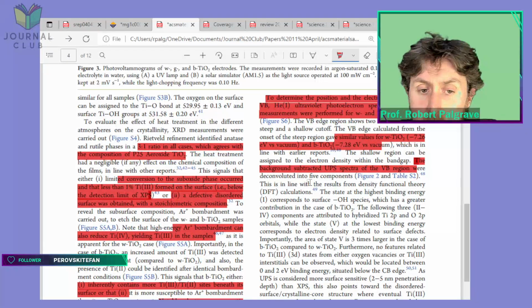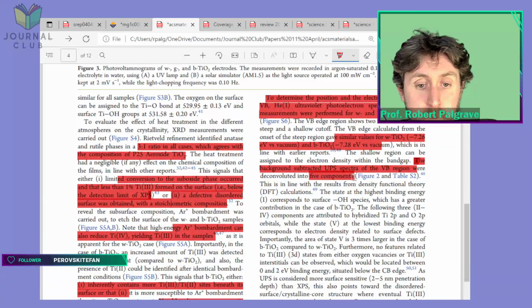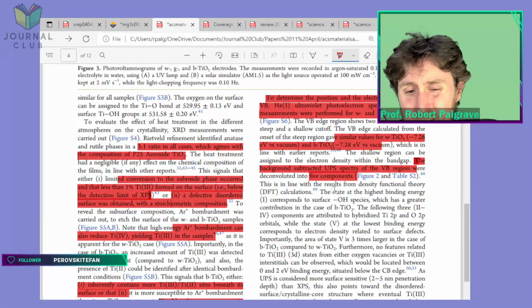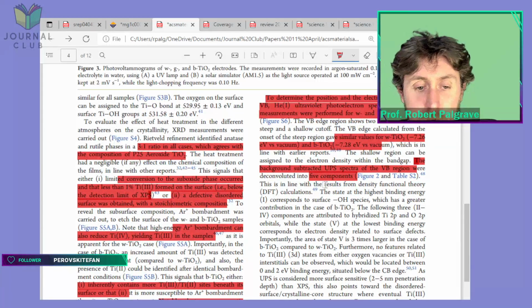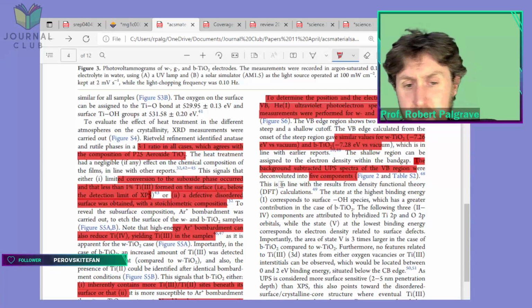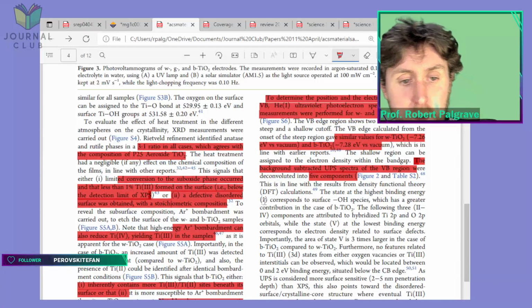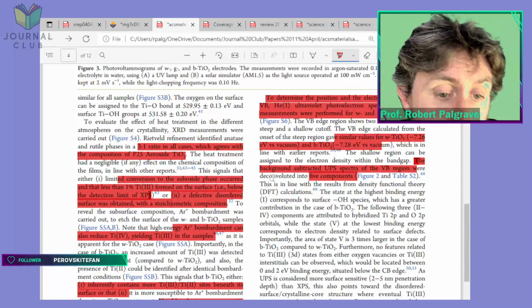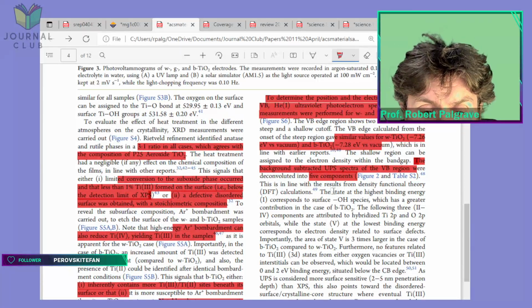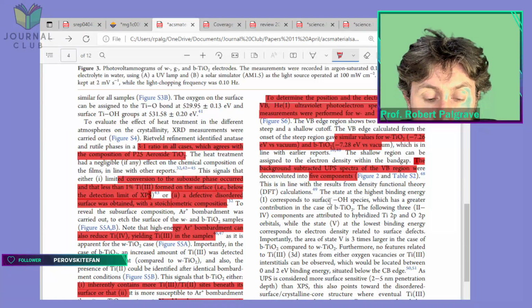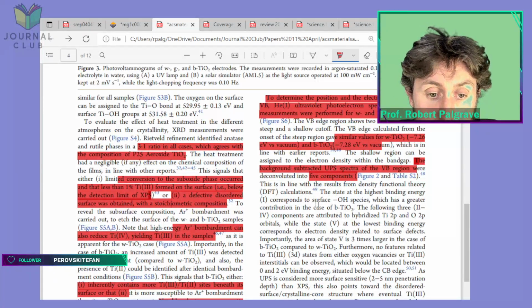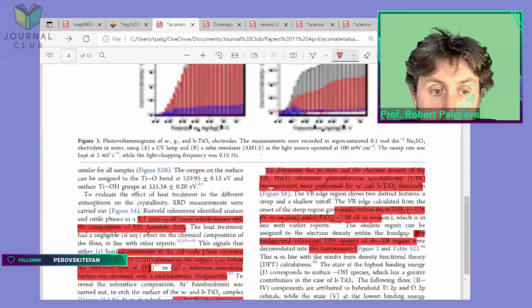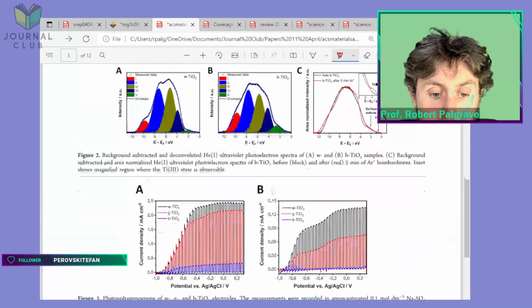I'm pretty sure the DFT paper is not going to say there are 5 components in this valence band, because that's not language DFT people speak. They like to talk about partial densities of states. I don't think they're going to say there's 5 things. But anyway, maybe they will. The state of highest binding energy corresponds to surface OH species, which has a greater contribution in the case of black TiO2. Component 1 is surface OH species. Okay.